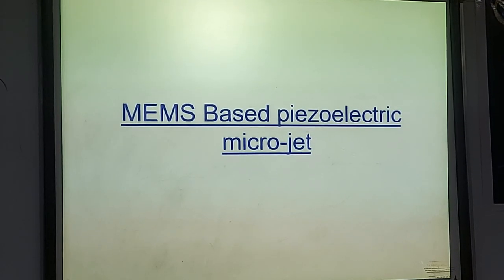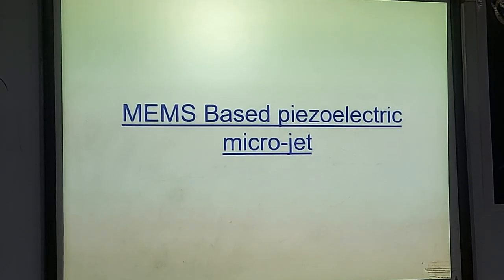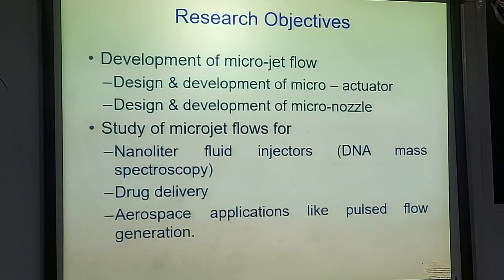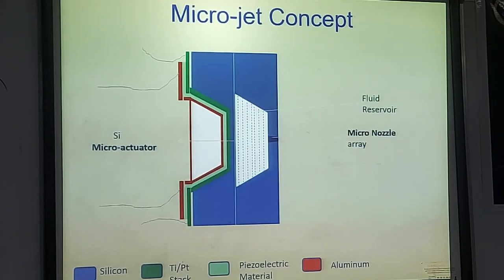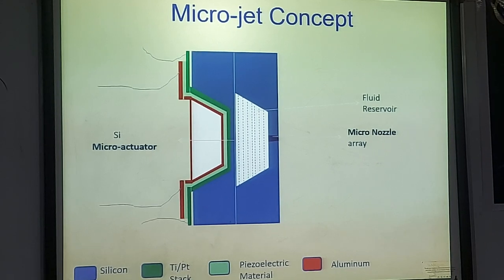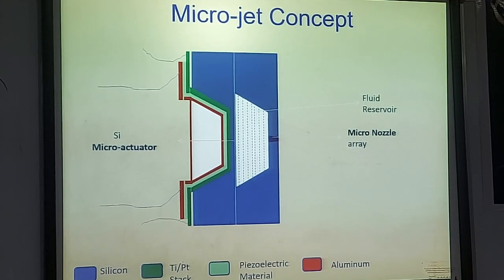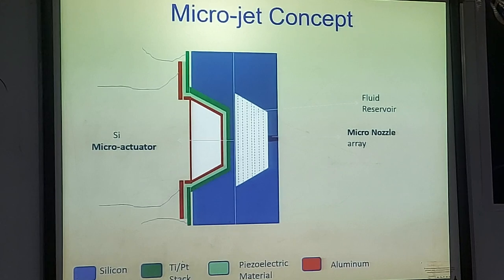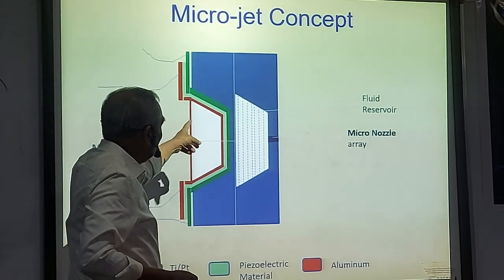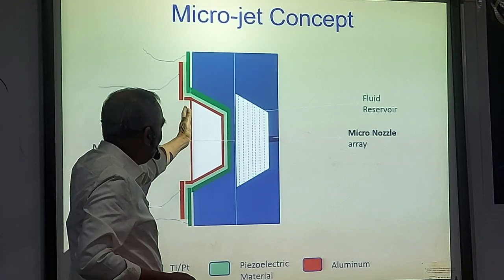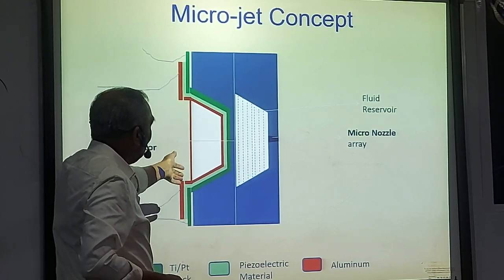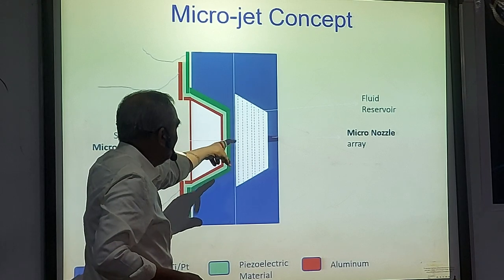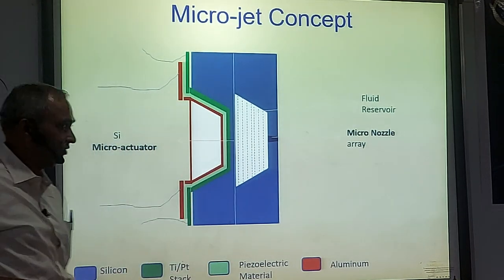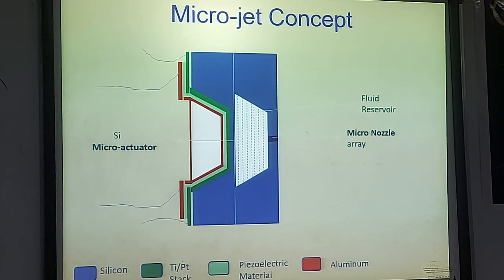Lastly, I thought I will touch upon the MEMS-based piezoelectric microjet, which has several applications. Maybe another 1 or 2 minutes I can take. This is a silicon-based technology where we have two diaphragms. This is the lower part, onto which we deposited a piezoelectric thin film sandwiched between two metal layers. On the top is a silicon diaphragm with a small hole of the order of 2 microns. Both these diaphragms are of our fabrication, and they are bonded. This is the interface.